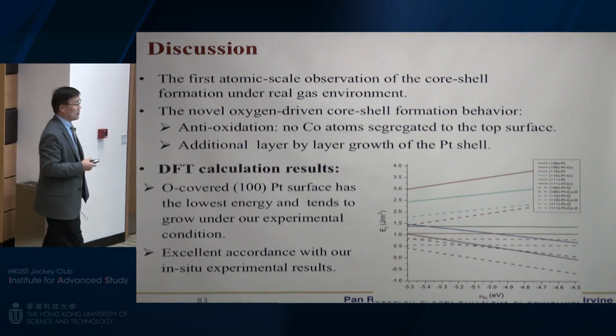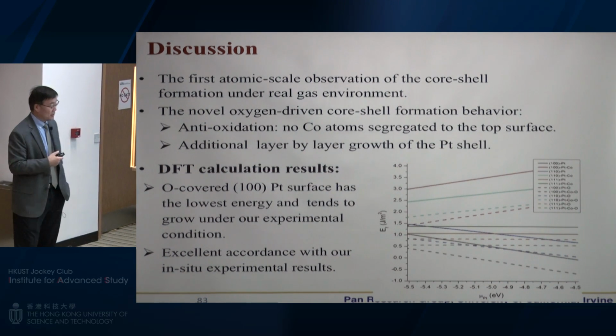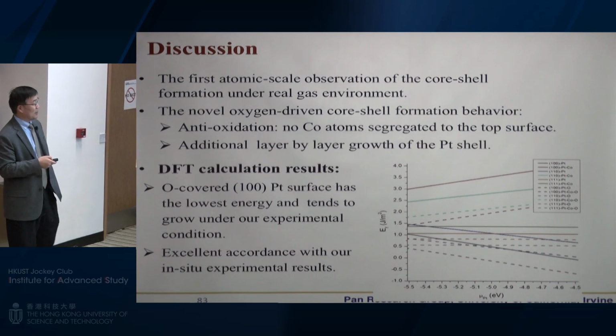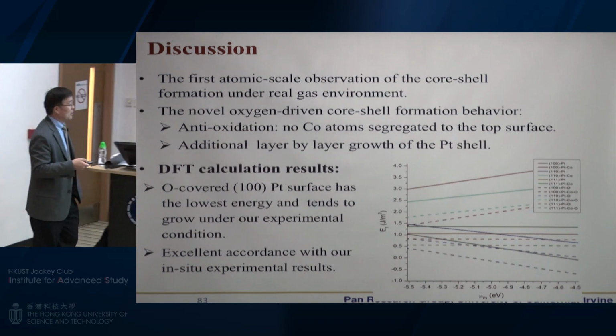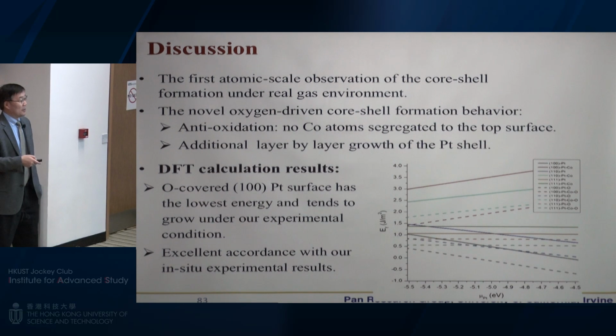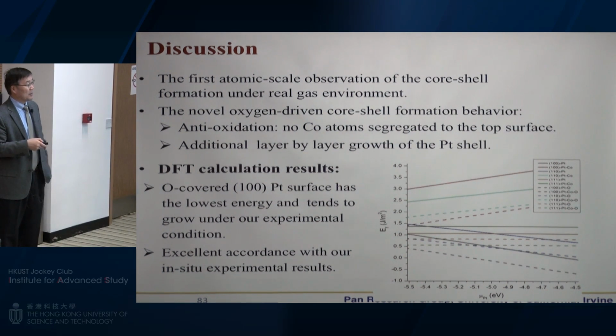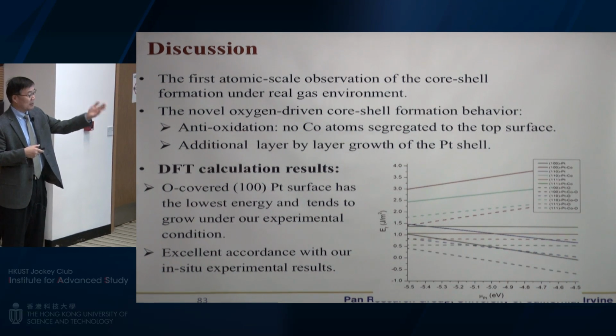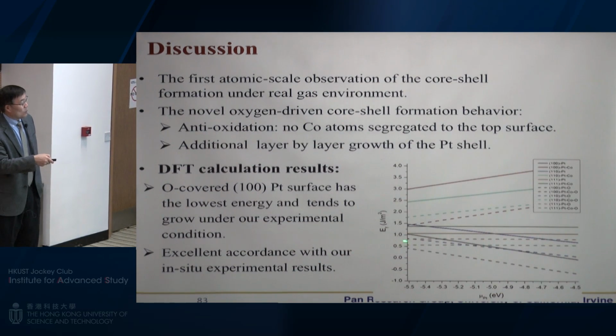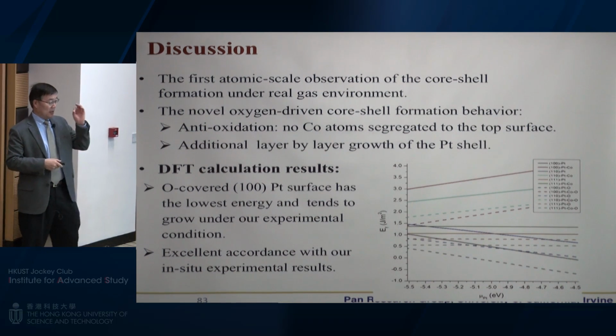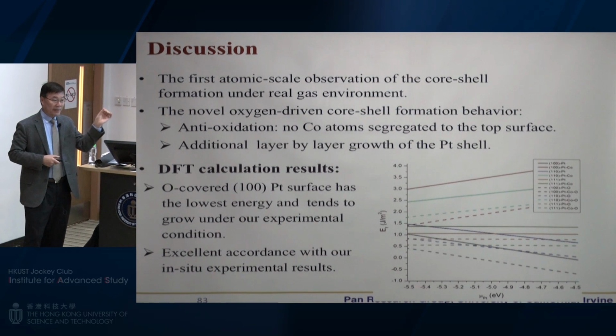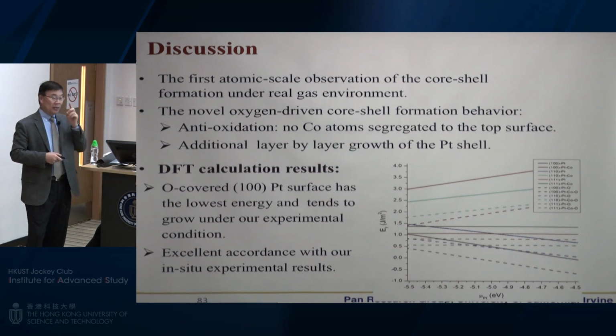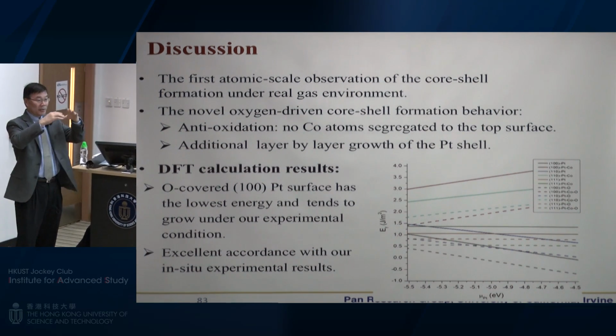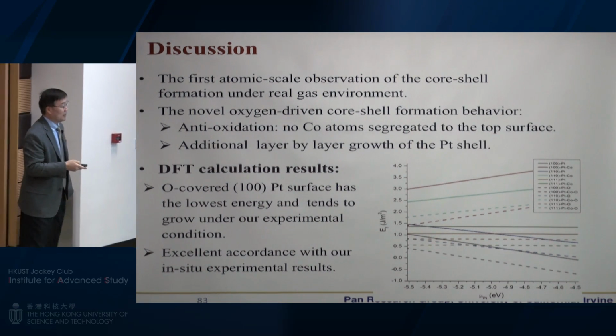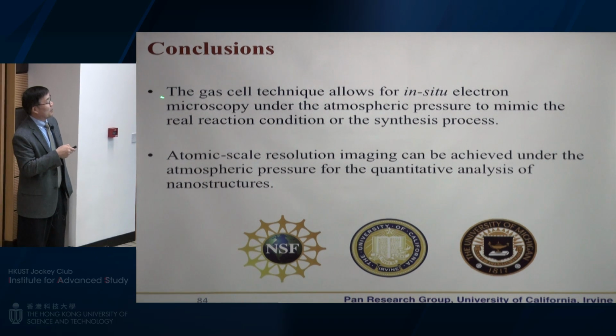When we got to this experiment, we talked to Professor Ruqian Wu in physics, a theoretical scientist with expertise in first-principles thermodynamic calculation for different materials. He worked with Goodenough for many years, so he knows this system very well. He calculated surface energy with different compositions and different atmosphere conditions. It turns out the 100 phase has the lowest surface energy in the oxygen atmosphere. The other phases' energy is significantly higher. Only platinum 100 has a low surface energy, so that it can form to cover this platinum cobalt particle and stabilize it in oxygen atmosphere. I think that was what I wanted to say about catalysts.